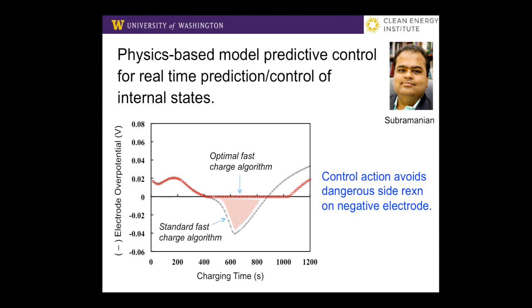If you're trying to do a fast charging algorithm for a lithium-ion battery, avoiding internal states that are dangerous. This negative going standard fast charge, that's a state that for electrochemical reasons can be dangerous to the health of the battery and can lead to fires. And so you can predict these internal states at each electrode and all the physics and control around avoiding those states. So if your model is really good and you can update your parameters effectively, this is a pretty good way to get some insights into what's going on inside of the can or inside of the pouch.